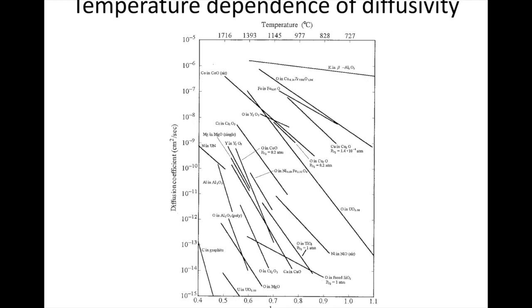But the one thing to keep in mind here is with almost all of these, if not all of these, you see that they're linear relationships. So that's important to kind of keep in mind. That means that this expression that we've developed, this empirical expression that we developed for diffusivity as a function of temperature, is holding, right? It's linear throughout, and therefore it has a single slope. And so that's something to keep in mind, is that the activation energy is the same throughout.